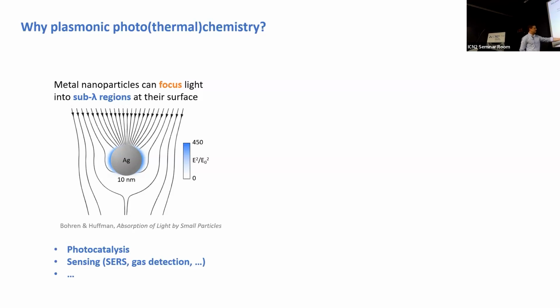Of course, this is also the basis for a lot of the surface-enhanced Raman scattering techniques, which is proportional to E to the power 4. So if you have a plasmonic enhancement, you can even do single molecule vibrational spectroscopy with SERS. We use it in our lab also to do gas detection, because anything that happens in the high intensity plasmonic field will be very visible optically. This is the first reason.